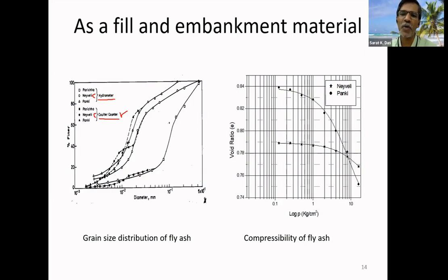Even if you look at the compressibility, how quickly it reacts. If you go with class C, which is cementitious, hardly any change in void ratio occurs. But if I am going for class F, obviously I expect rearrangement or pore pressure dissipation, through which we can get the compressibility of the fly ash. So this also indicates that class C fly ash reacts immediately, which is called its self-hardening property.